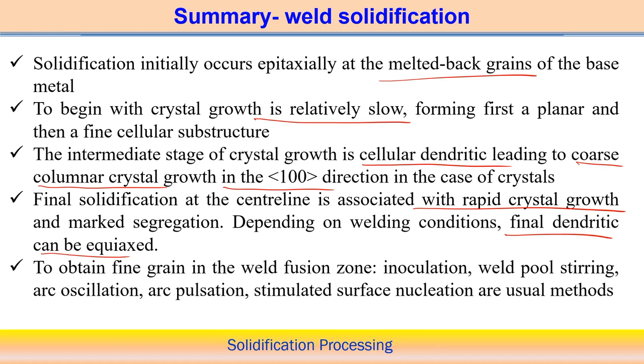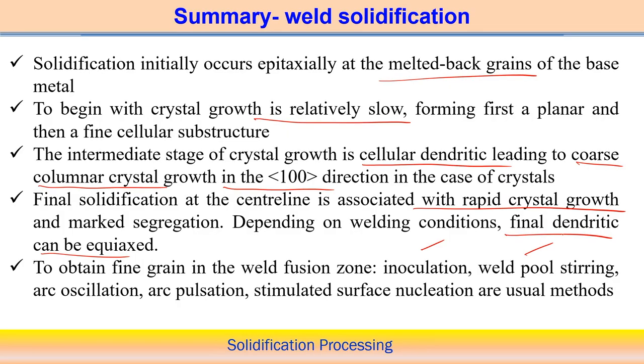Of course, depending upon the welding conditions, a final equiaxed dendritic structure is possible. But in general, if you want to obtain a very fine grain structure in the fusion zone, there are different ways to promote the formation of equiaxed fine grains. One is adding some inoculating agent, such that nucleation starts at different positions at the same time, the rate of nucleation is much higher, and it is well distributed throughout the structure. Another point is the weld pool stirring effect. If we put in some external stirring mechanism, it also enhances the nucleation process. It can also be done by arc oscillation, arc pulsation, or a continuously varying dynamic arc, which helps to increase the rate of nucleation.